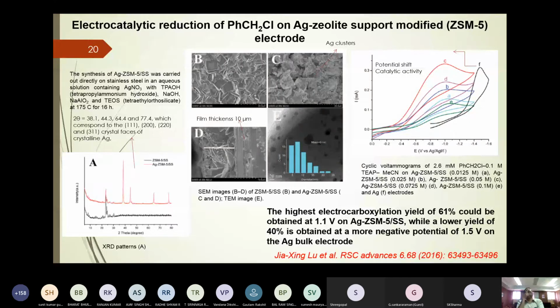XRD confirms the formation of a silver zeolite obtained on stainless steel. The SEM picture also shows the size, for example, a film thickness of 10 micrometer. So of the size like that. Then we have tested this molecule.